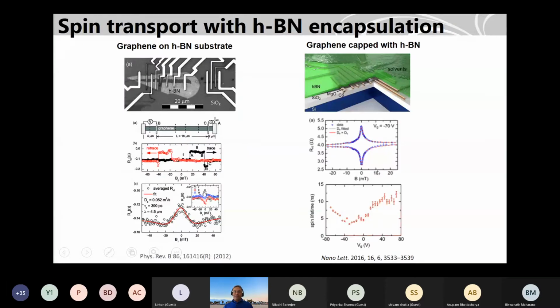So how to get better spin transport in such graphene devices? For example, this is work with boron nitride graphene. You see very long distance spin transport. So it's quite close to the CVD graphene I showed. So that's very interesting, that the CVD graphene on silicon oxide substrate also can match the exfoliated high quality devices. That is quite surprising and also can be useful.